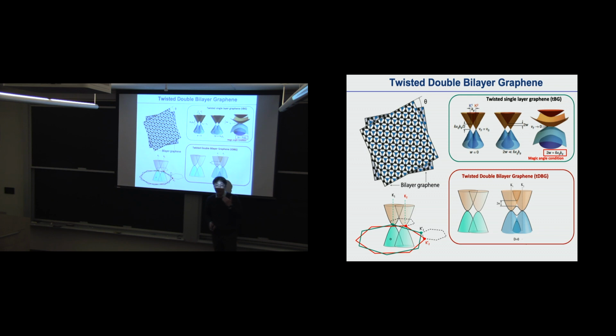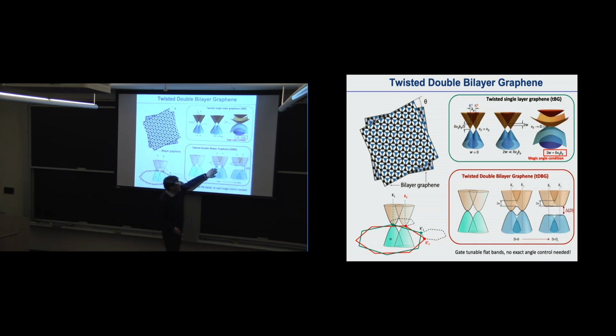But there is an additional knob that we have in bilayer. In Bernal stack bilayer, there's inversion symmetry in this lattice. However, by applying an electric field, you can break that inversion symmetry, and the band gap is deformed. You can actually tune this deformation of the band with the electric field applied in the vertical direction. This can be done simply by putting top and bottom gates in there.